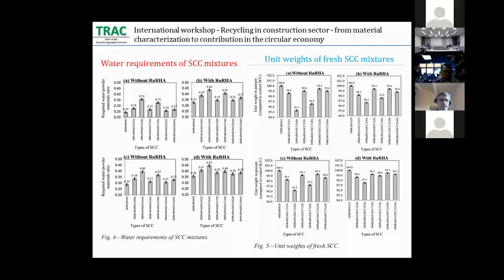In the results of water requirement in terms of water-powder ratio for achieving self-compacting concrete, the water requirement of self-compacting concrete mixed with rice husk ash and calcium carbonate can be seen on the left side of the figure. It can be seen that the water requirement of concrete containing calcium carbonate is higher than the water-powder ratio of the controlled self-compacting concrete, in both the calcium carbonate and rice husk ash cases.